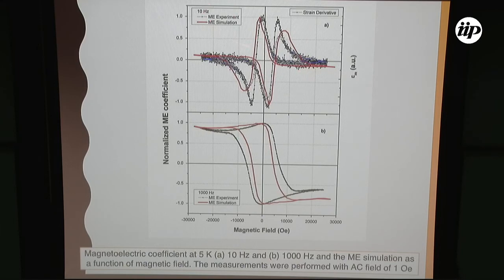In the case of low frequency, a quite strong strain is observed. The derivative of the strain, in blue, is very close to the shape of the magnetoelectric coefficient. And at high frequency, this curve is obtained. It is not in good agreement, probably because my sample is not an absolutely polycrystalline sample. It does not have a perfectly homogeneous distribution of grain size in the sample.